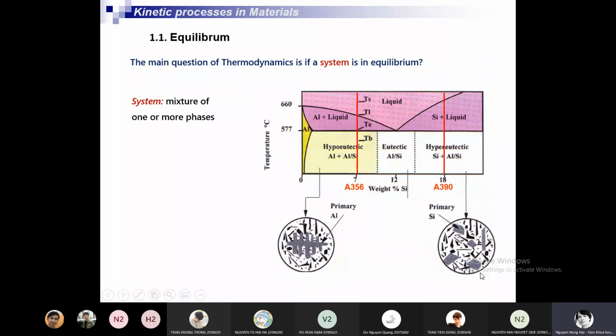And if we have the eutectic alloy, about 10% of the silicon, for example, the alloy A413, so we have the structure is eutectic. So we have the silicon in dark embedded in the aluminum, that is in white. It's an eutectic structure, consists of two phases, silicon and aluminum. You see? So eutectic is not the phase, it's the structure, not phase, but structure, because there are two phases here. So, for example, for this aluminum and silicon system, we have quite a different microstructure depending on the chemical composition.